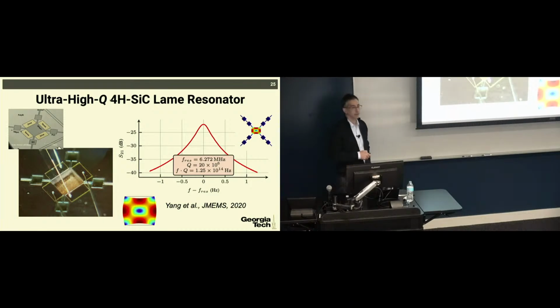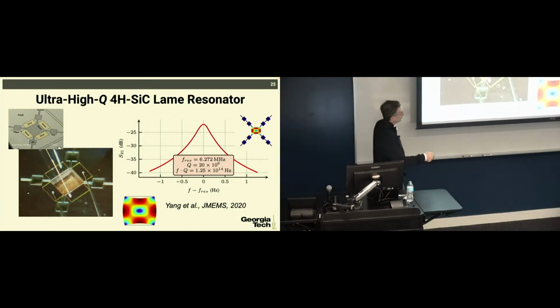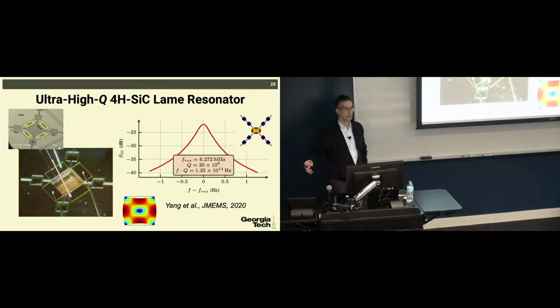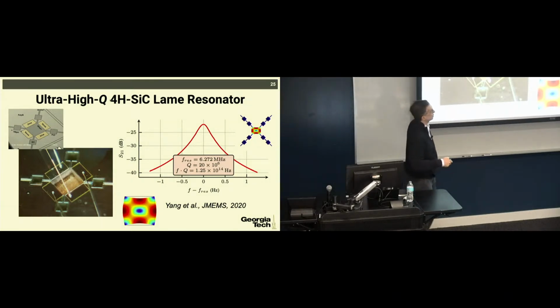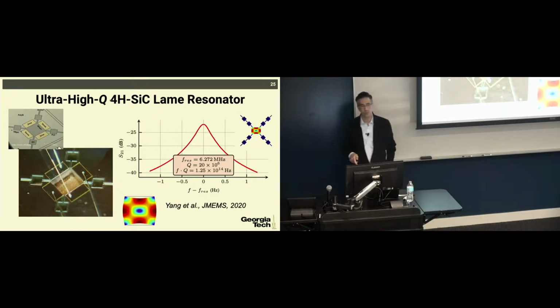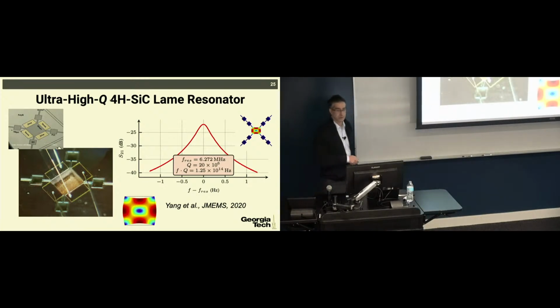Well, this is why we did it, which was so exciting back in 2020 when we got this result. So this is a square lamé resonator. Do you remember those distributed lamé ones? It is a bunch of these next to each other. This one is only one of those lamé modes, as you can see here. And we have phononic crystals integrated in the support structure to minimize the acoustic loss into the substrate. And what we measured was a Q of 20 million at 6 megahertz. Okay? So this is, to date, the highest acoustic Q that is measured in a MEMS resonator.